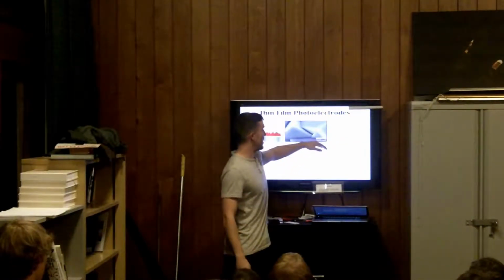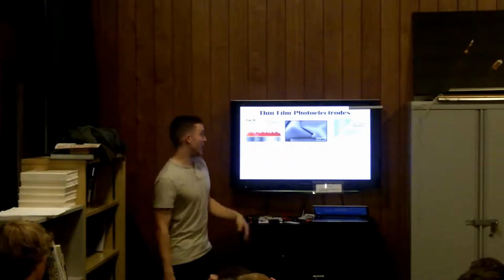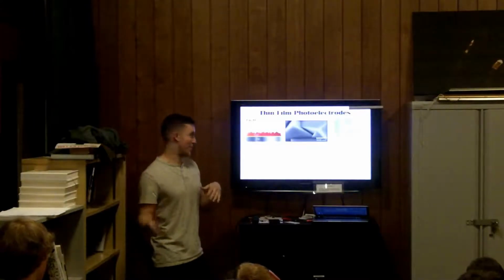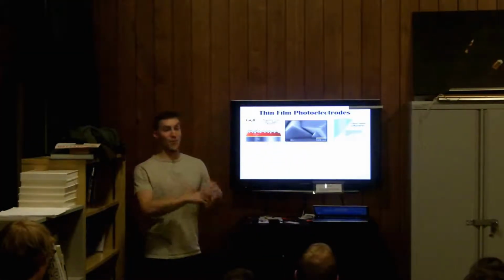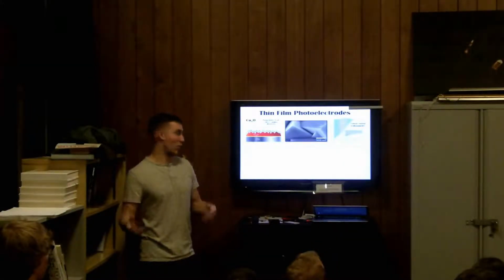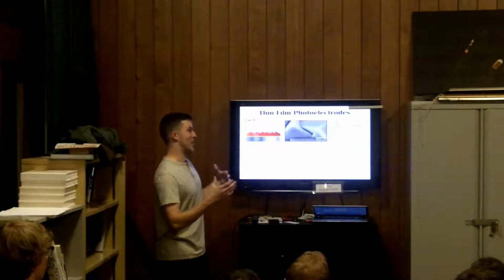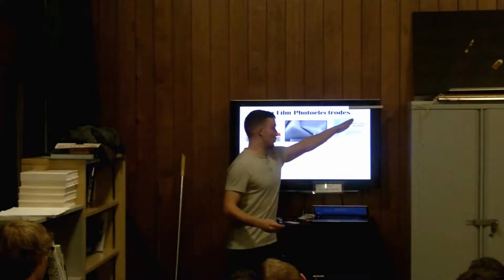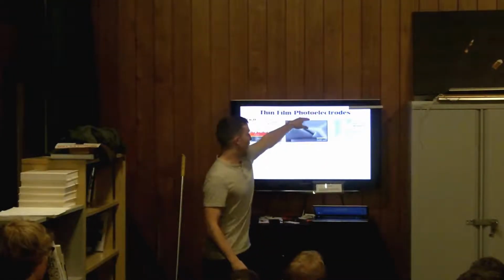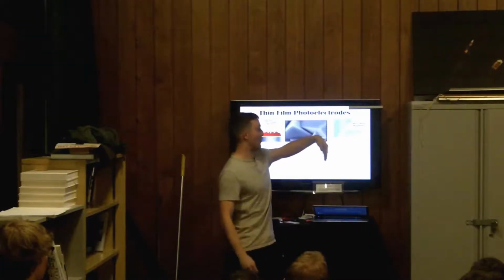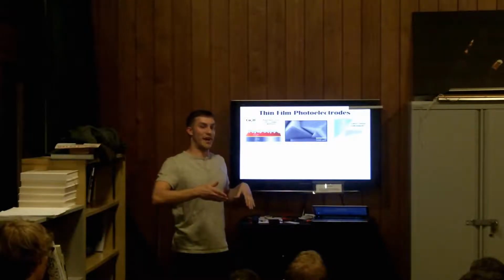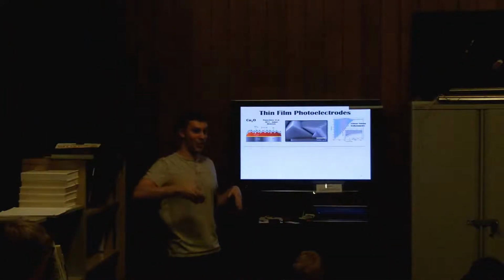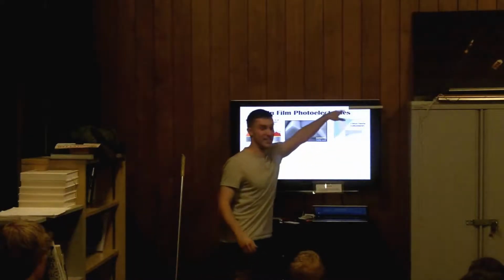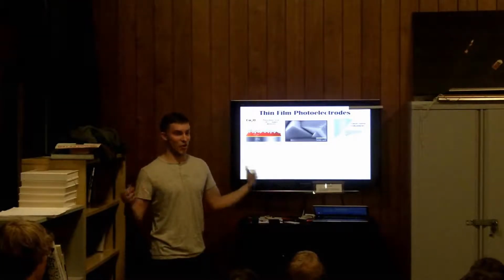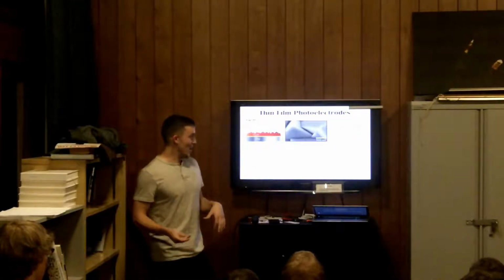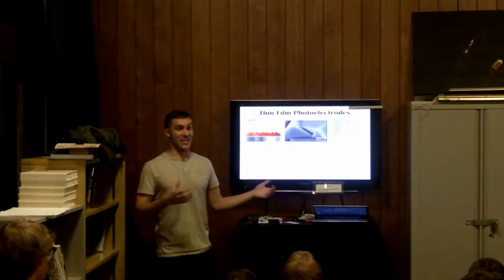So this axis here is the current that we're getting through our circuit. And in this case, it's negative because of the way the signs work out in the convention. But a larger bar means we got more current going through the circuit and more energy that could be stored. And I like these graphs because they're very pictorial in that we do light chopping. So you see the part of the graph where every 5 seconds or so they have sort of this gap where it goes back to 0. That's because they block the light for 5 seconds. And then when they take the blocking material away and let the light shine back onto your material, you immediately see the current increase. So you know that the energy you're getting is all coming from the sunlight or the simulated sunlight. So I think it's really a nice way of representing that all of your energy is actually coming from the light itself.